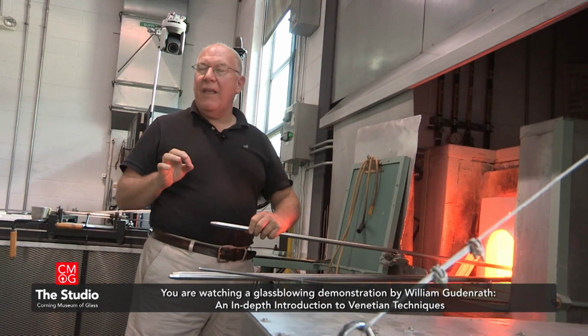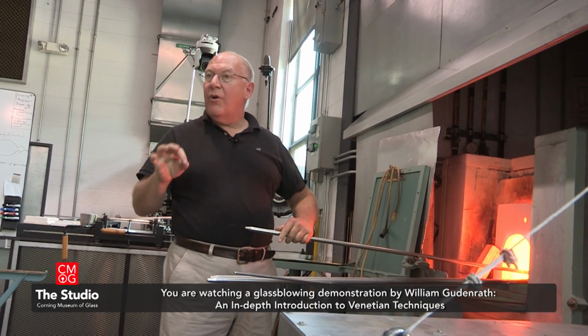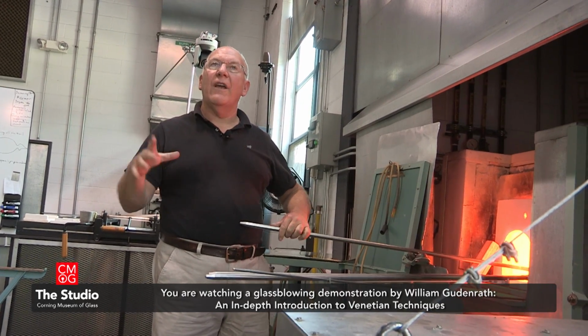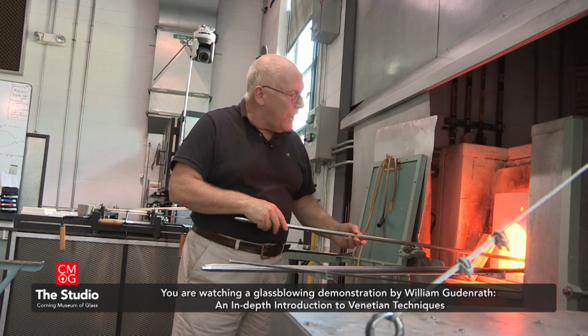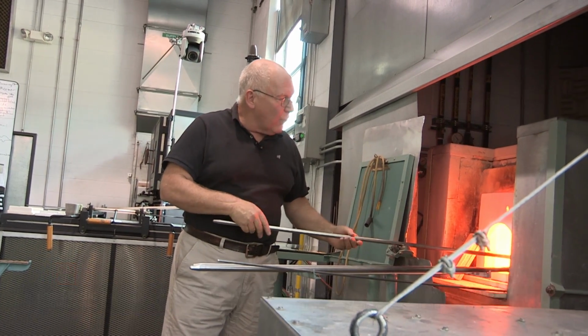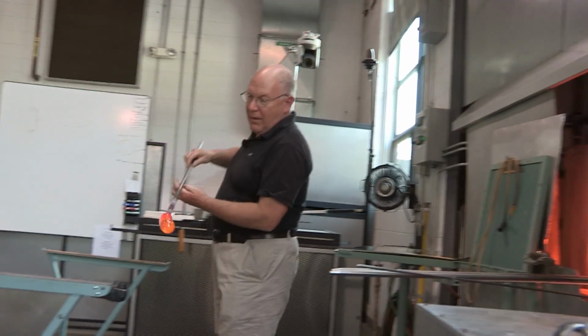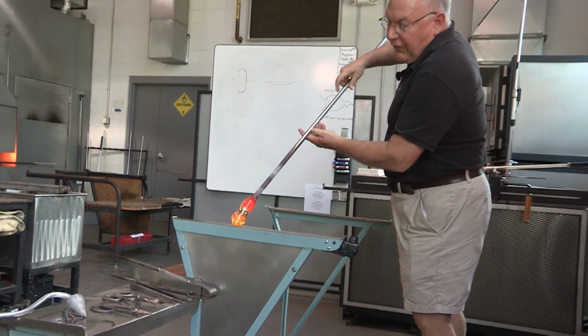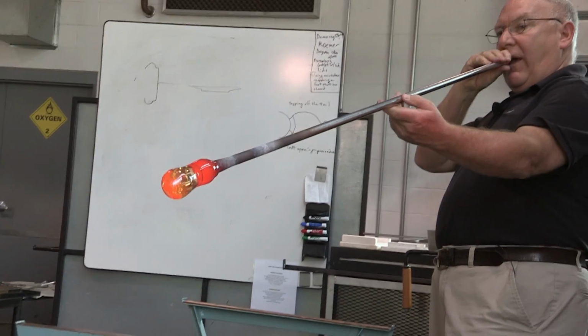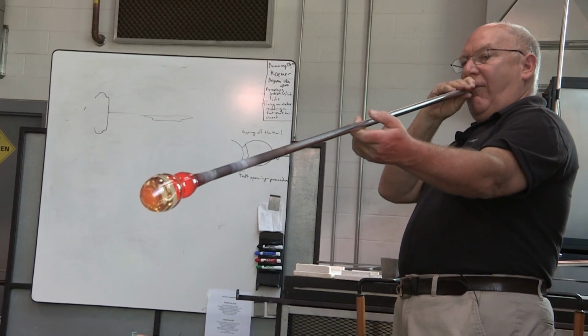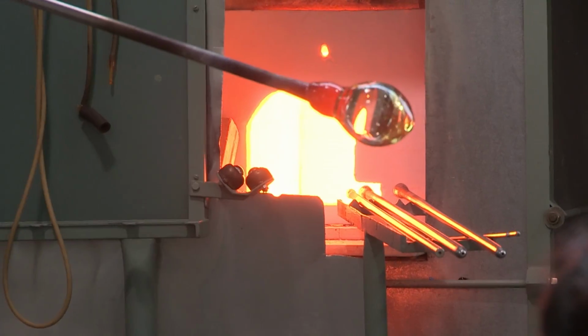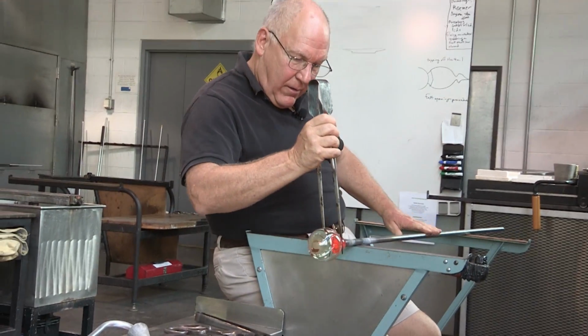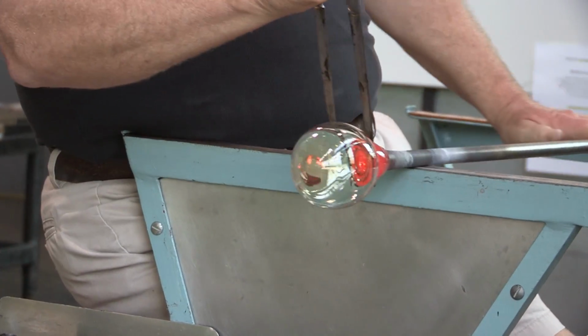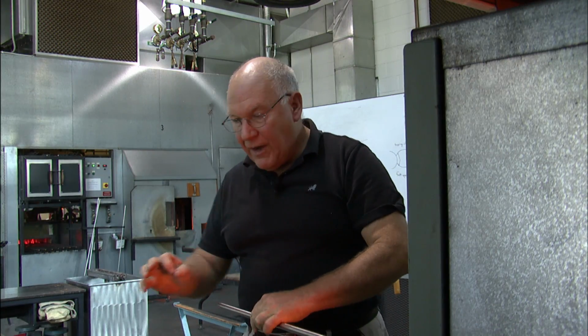And I'm going to do this like any Venetian would do. I'm going to blow a sphere, put a neck in it, then re-soften the sphere and turn it from spherical into an oblate spheroid. That's roughly the shape of the Earth. I'm over the tip again to make sure that this stays chilly and thick. Blow halfway to final size. I start the neck. I'll blow it up a little bigger, then finish the neck.